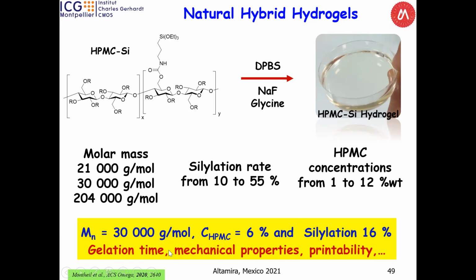The best one, if we want to summarize between gelation time, mechanical property, and printability to make 3D printing, was the polymer with 30,000 mass, at 6%, and silylation rate 16. So, by this way, it's possible to control. If you need something more flexible, you can decrease the silylation rate, you can decrease the concentration, or if you want to keep both here, you can decrease the mass. We have several solutions.